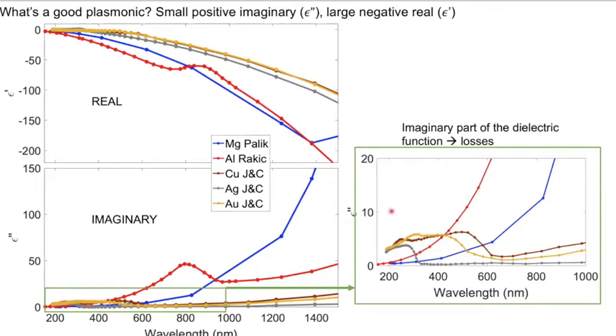And you have our usual suspects here, right? Copper is here, gold, nearly the same thing as copper, and then silver, very, very low losses in silver. And then here's my magnesium, quite low losses across the UV and visible, increasing losses in the IR. And here's aluminum, very high losses at around 800 because of an interband transition, where basically if you excited a plasmon, it would immediately decay into this interband transition. So it's very lossy.